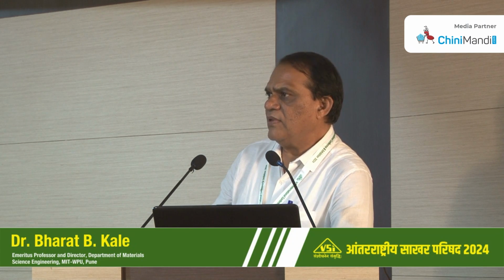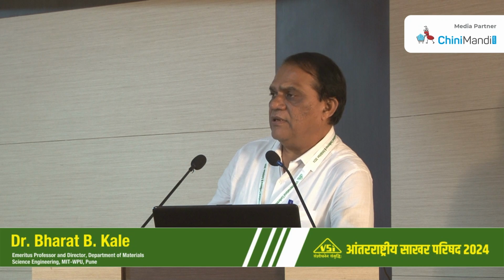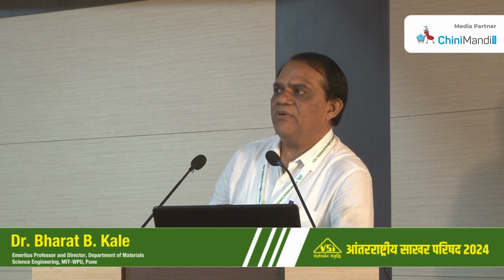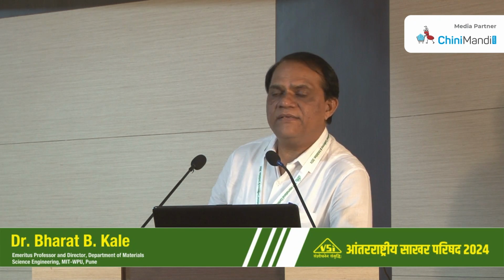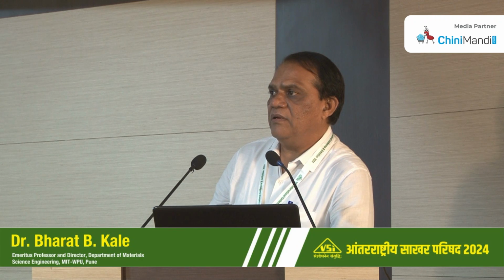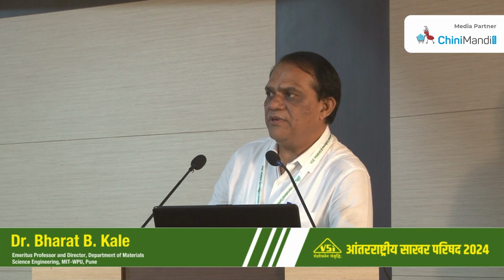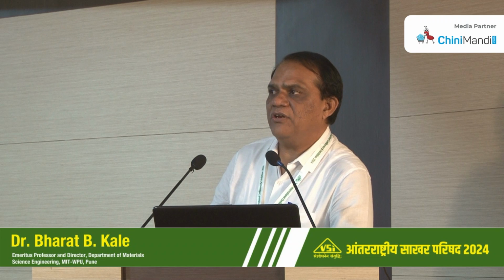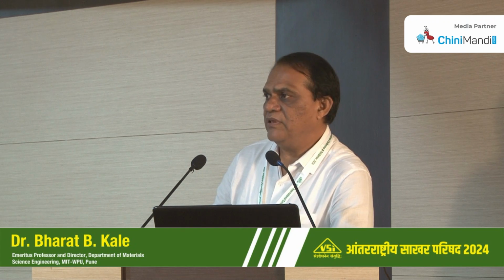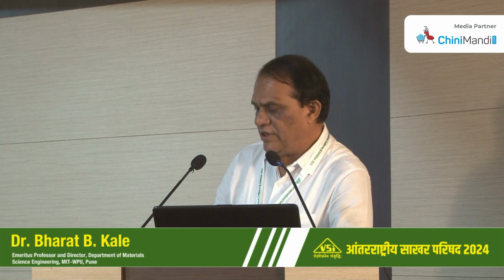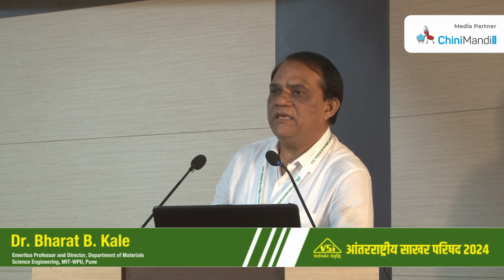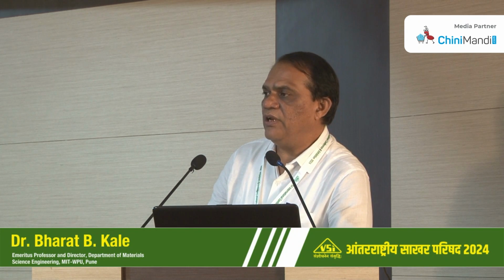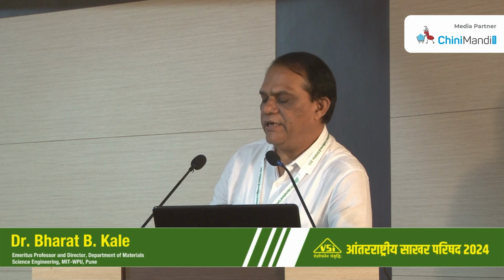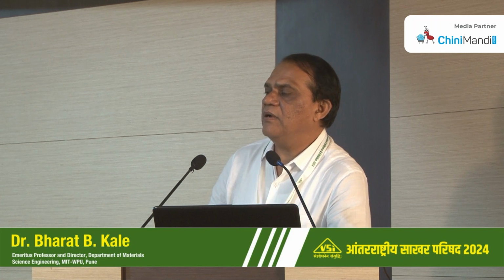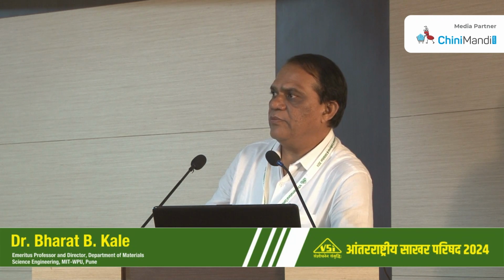We are more focused on oxide photocatalysts because they are stable catalysts, chemically stable as well as thermally stable. So modification of oxide semiconductors is very important. That we are doing, and we are tuning the band gap between 2.2 electron volts to almost 2.8 electron volts, so that the 400 to 800 nanometer range we are covering in